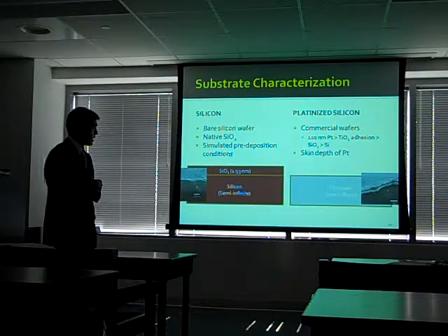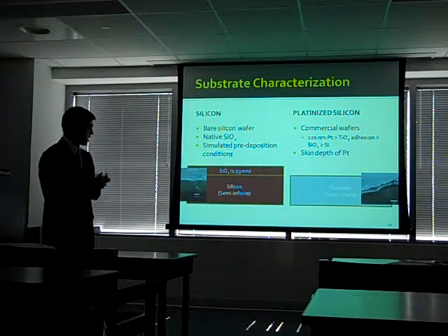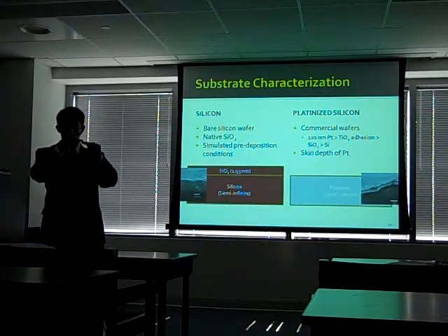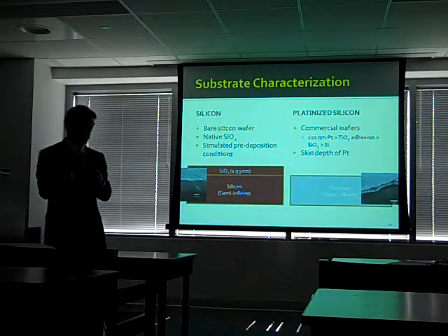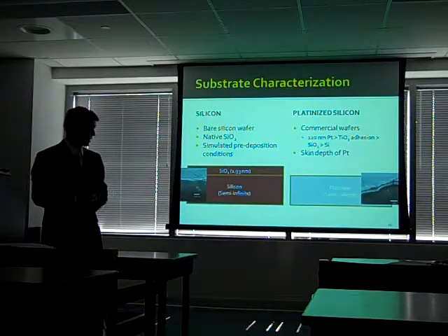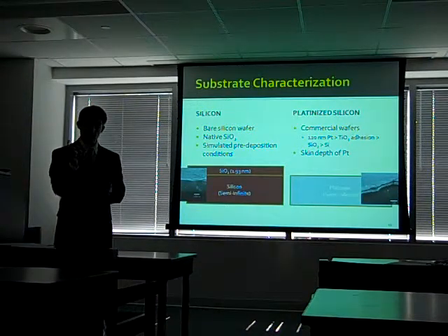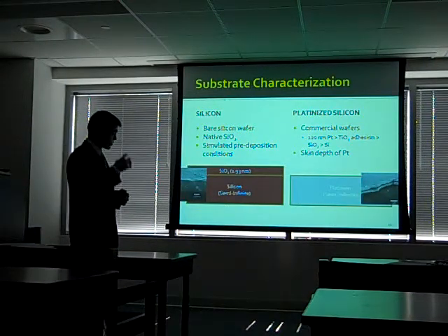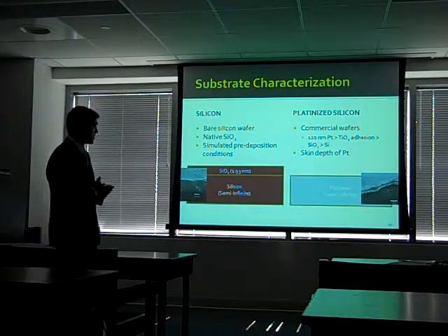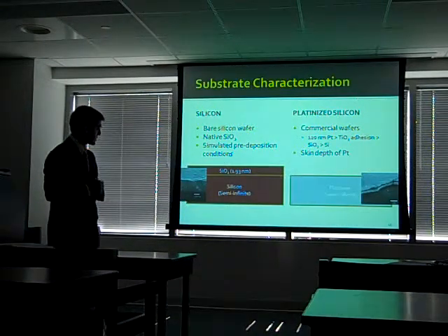And the platinized silicon substrate is actually a little different. The film is 120 nanometers of platinum on top of titanium dioxide, on top of silicon dioxide and silicon. And as ellipsometry is an optical technique, the skin depth of platinum in that frequency range is only 30 nanometers. So the result is the ellipsometer can't see past the platinum layer. So the substrate in this case is just modeled as a semi-infinite platinum layer.